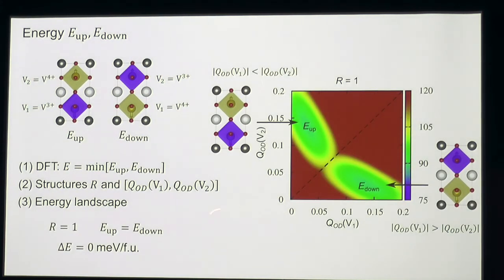This is the energy landscape for R equal to 1 as a function of the displacements of the two vanadium. We can see that this energy landscape is separated into two parts by the diagonal. In the upper part, it corresponds to the structure in which the vanadium 3 atom has a smaller displacement and its polarization is pointing up. And the other half corresponds to the structure with polarization pointing down. Because of the symmetry, the energies corresponding to the local minima are identical.